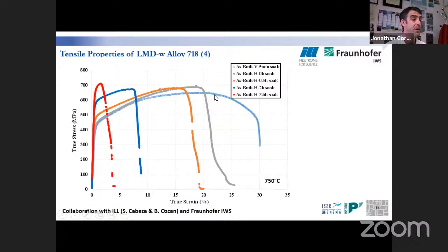We have 5 minutes soak time for vertical direction. 5 minutes, sorry, yes. We tested immediately the material here after reaching 750C. Half an hour, 2 hours, and 3.5 hours for the red curve. So what you can see is that we have an increase of the yield stress and a progressive decrease of the ductility.